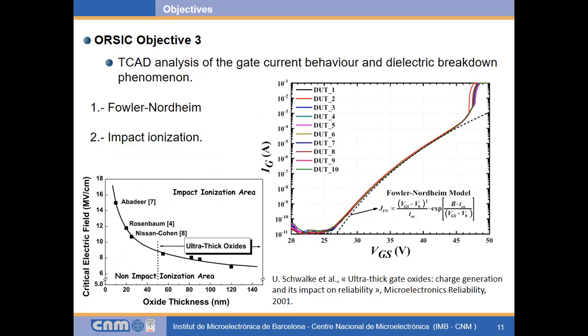We can observe in the picture on the right that around 43 volts, a deviation of the Fowler-Nordheim current model starts. And this corresponds to the change in the slope we have seen before, and also agrees with the picture at left. We see around 50 nanometers, which is the typical thickness of the oxide in power MOSFETs. We have that around 9 megavolts per centimeter, the impact ionization phenomenon is triggered. This agrees with the start of the deviation of the Fowler-Nordheim, and also with the change in the slope.